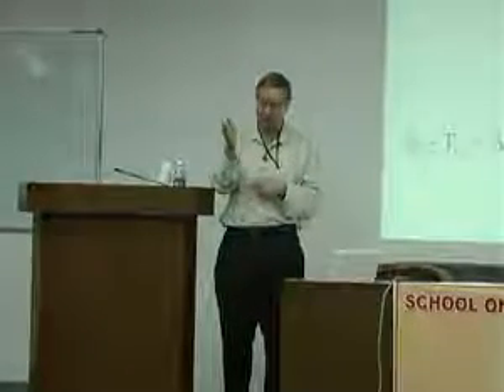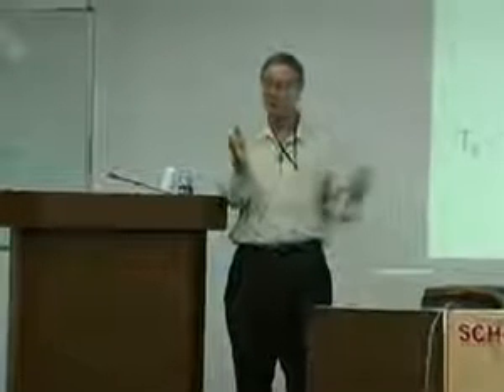You mentioned this Tg variation in different measurement techniques. Why is it happening? Well, one reason is that if I look at the dynamic response of the material, it's frequency dependent. So if I do measurements at different frequencies, I can get a difference in Tg. Somebody who does a dynamic mechanical or a dielectric measurement might do it at 10 hertz, and that's faster than the normal, say, DSC scan.